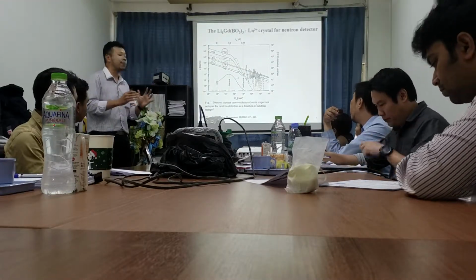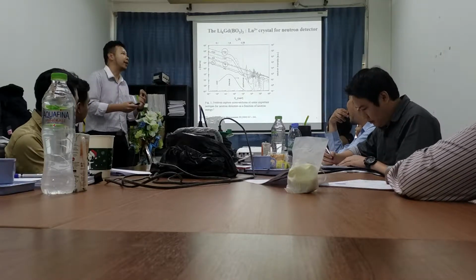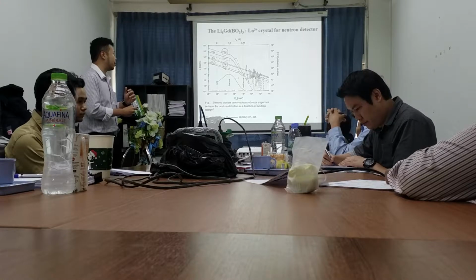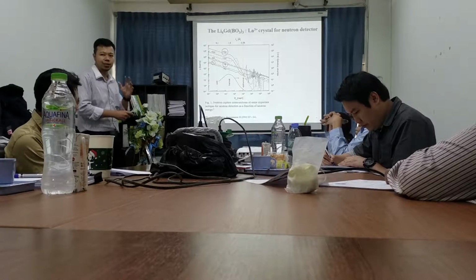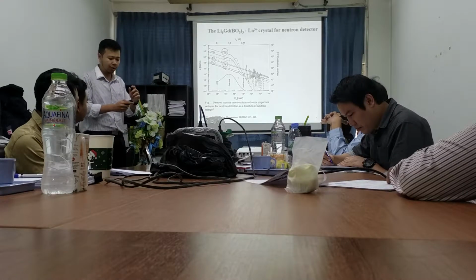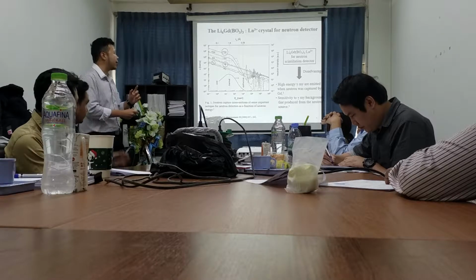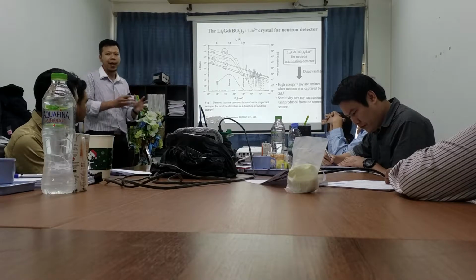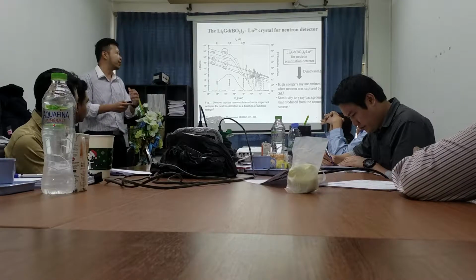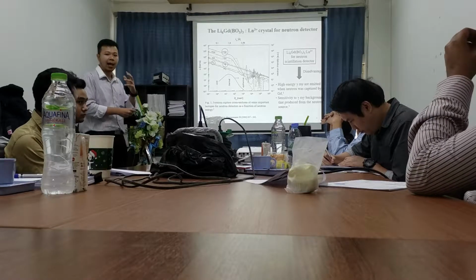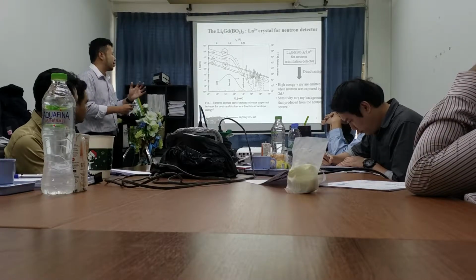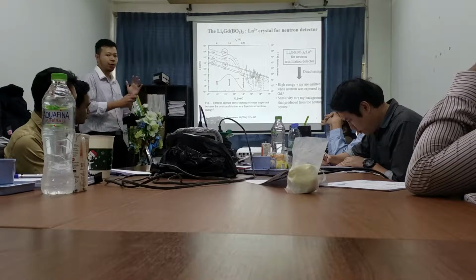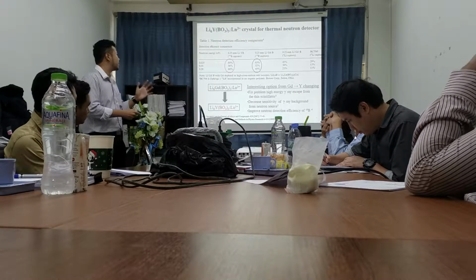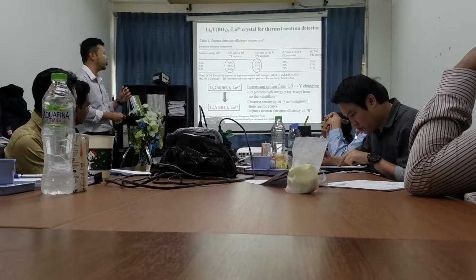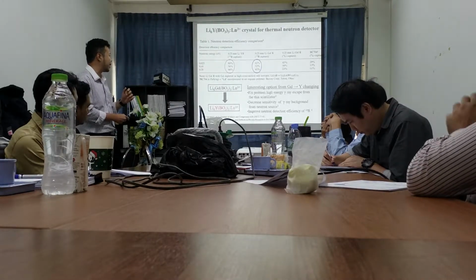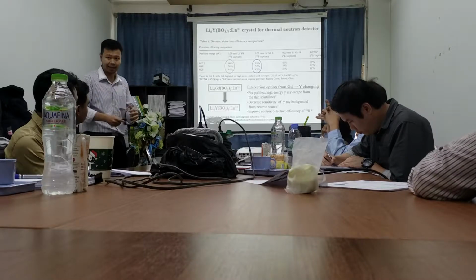Starting with the introduction about the host of my thesis. For the host material, I'm interested in the lithium gadolinium borate crystal, because lithium, boron, and gadolinium isotopes have a high neutron capture cross section. At first, lithium gadolinium borate crystal doped with lanthanide ions was prepared and studied, but it had some disadvantages, because when neutrons were captured by gadolinium, it emitted high energy gamma rays, and this material is sensitive to the gamma ray background produced from the neutron source. Therefore, these crystals were improved by changing from gadolinium to yttrium. Lithium yttrium borate crystal doped with lanthanide ions showed good properties for neutron detection.